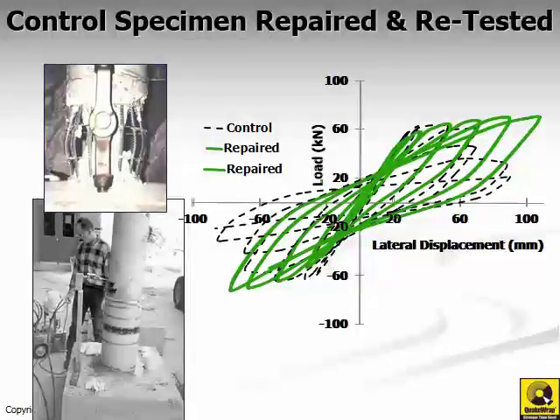save that column. So the previous column that you saw in the previous test, we actually cleaned up the area of the damaged area, and notwithstanding the fact that this column was a little bit shorter, now we did not try to stretch or straighten the column, but we dry packed some concrete in that bottom portion of the concrete and got much of that annular space, or the space was filled with grout. And then we wrapped the lower 2 feet of the column with some FRP fabrics in the hoop direction, and injected a resin in that area to make sure that there are no voids or cracks remaining.